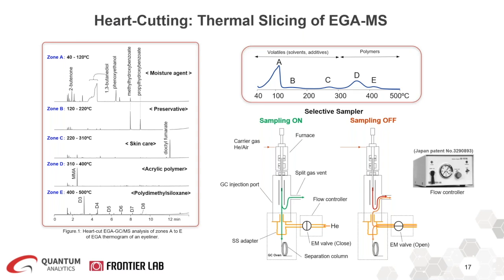On the right-hand side, you can see an EGA thermogram of an eyeliner that can be sliced into 5 different zones or peaks, zone A to E. The heart-cutting technique allows us to program the pyrolyzer furnace into 5 temperature zones in this case, and obtain separate GCMS chromatograms to identify the components in each zone. So the analysis of each thermal zone yields a chromatogram containing only those compounds evolving from the sample of the selected temperature range. Figure on the left shows each zone and the corresponding identified compounds.